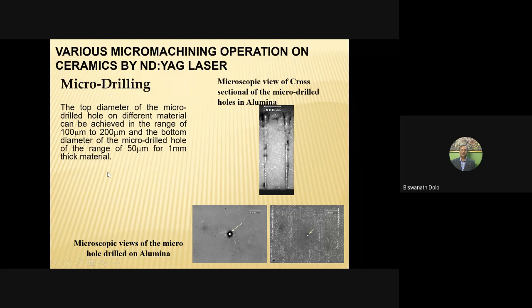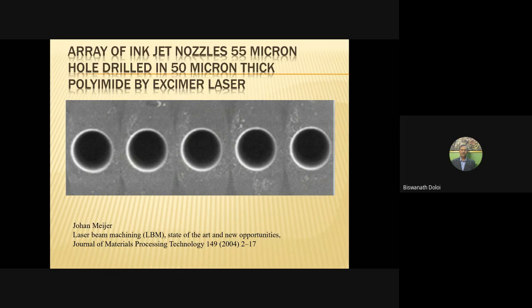Sometimes we require a taper hole, and for that you can apply laser micro drilling. And this is the hole drilled by excimer laser: a 55 micron hole drilled in a 50 micron thick polyimide sheet, an array of inkjet nozzles. For inkjet nozzles you require an array of holes, and the size is 55 micron, thickness is 50 micron. That is done by excimer laser and the material is polyimide. You can refer to this journal.